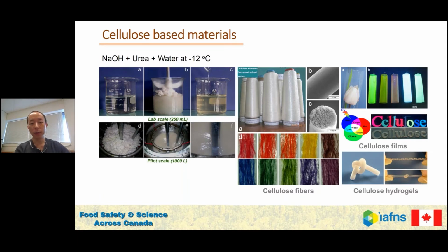So just a little bit more information about those solvents we are using. For the sodium hydroxide urea water, we can dissolve cellulose very quickly, in 5 to 10 minutes, and we can enlarge the production to industry scale production. This method was invented by my PhD supervisor, Professor Lina Zhang at Wuhan University in China.